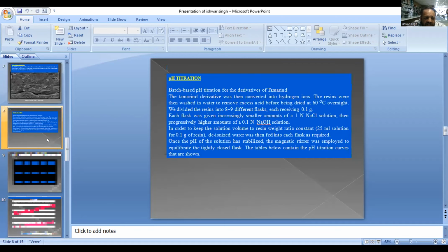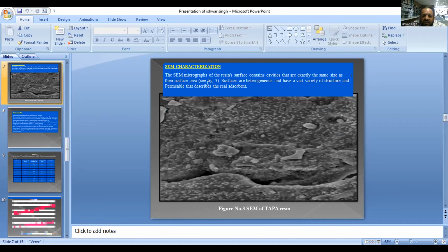This is the SEM. I have taken the SEM micrograph of the resin surface. It contains some cavity-like structures. These are small cavities around the whole resin that show the absorption capacity, more and more absorption capacity. The surfaces are heterogeneous, with a vast variety of structures, and permeable. Due to these cavities, the structure is permeable and can pass one thing and hold the other. This shows the real absorbent structure of the resin.